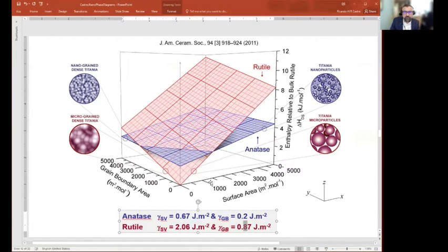Oh, so does that mean that it really matters how sintered my materials are? Yes, it will matter how sintered they are in determining the stable polymorph at that condition. So if I have free nanoparticles versus partially sintered nanoparticles, they will have different stability predictions.